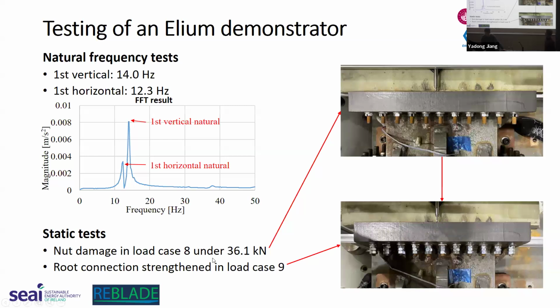Here are some observations from during the loading. Since we decreased the load steps, we observed the first damage of this demonstrator at a load of 36 kilonewton. This damage is also damage of a steel component, not the composite parts. It's a nut damage. We observed some nuts get damaged, and we had to replace them. Considering that we want to break the composite material, we added more nuts around these bolts and repeated the last load case.